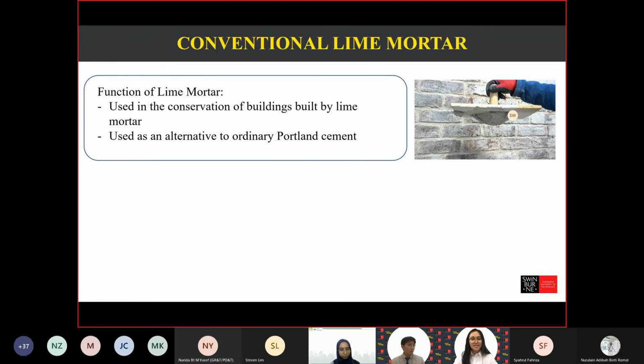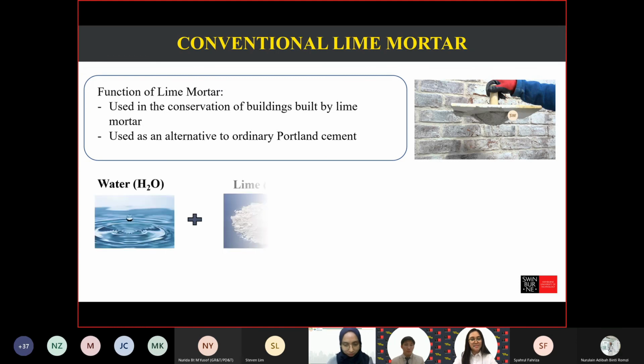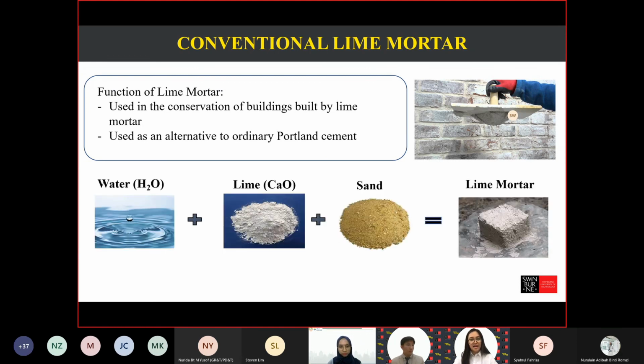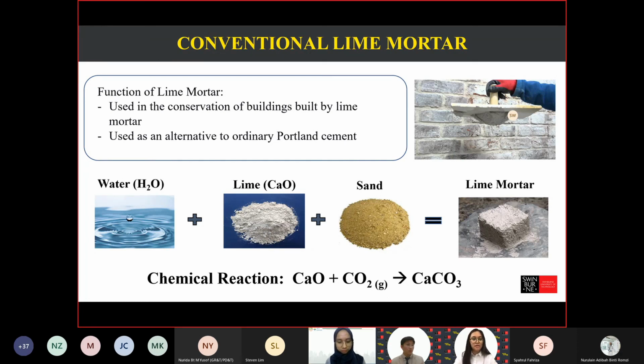Lime mortar is used in the conservation of buildings built with lime mortar itself and also as an alternative to ordinary Portland cement. Conventional lime mortar is made of water, lime and sand. The carbonation of lime mortar with atmospheric CO2 produces calcium carbonate, which binds the sand to form the lime mortar. CO2 uptake in this reaction is limited by the contact area and also the CO2 diffusion rate.